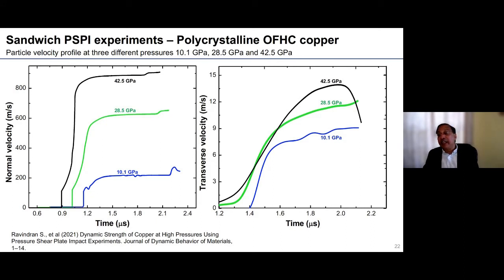So we need to have this very accurate measurement system, this heterodyne transverse velocimetry, using this technology of the photonic Doppler velocimetry to be able to resolve such low velocities at these high impact speeds. So now, as in the conventional plate impact experiments developed by Clifton, we can't directly infer the strength of the material. Now we have to do additional numerical simulations, and the results for the copper are presented in this paper, which was just published recently.